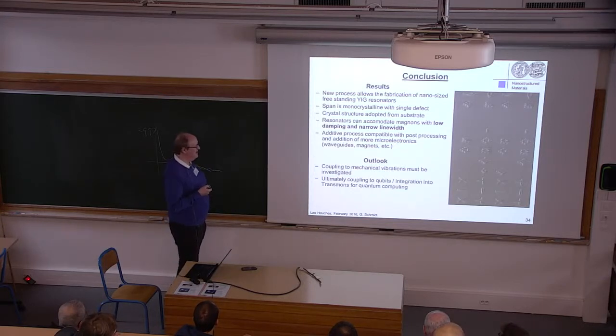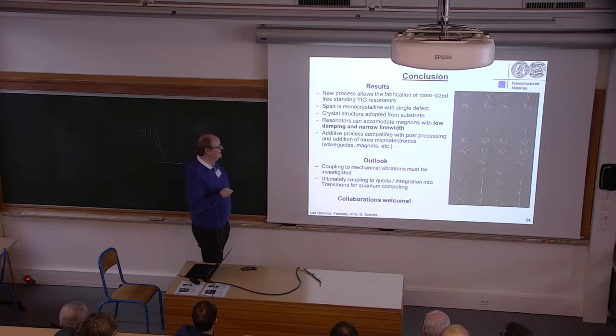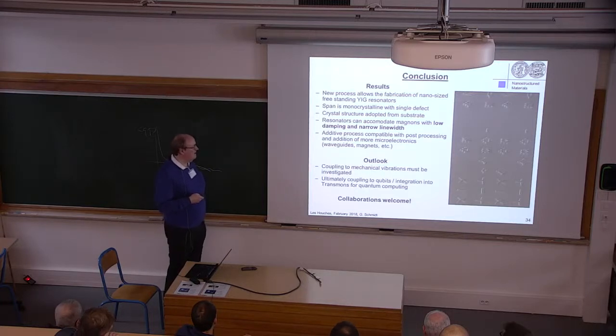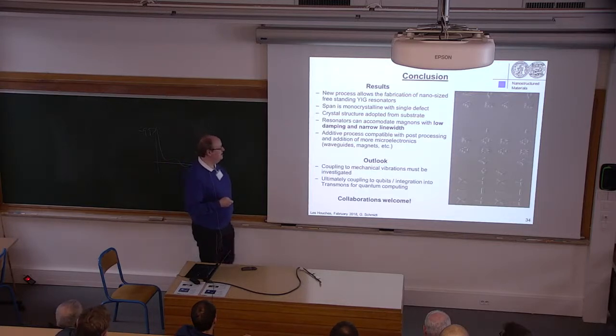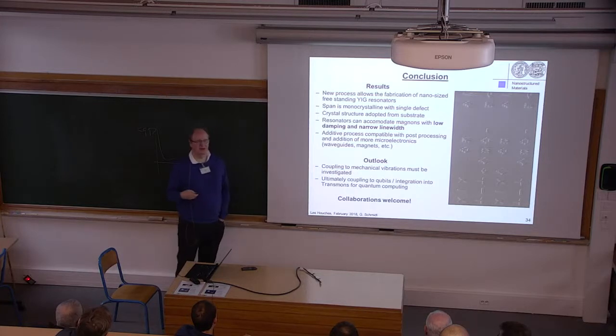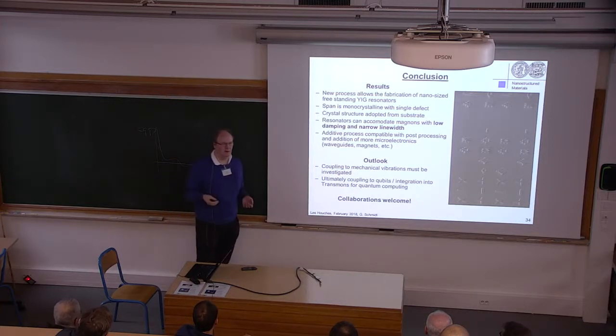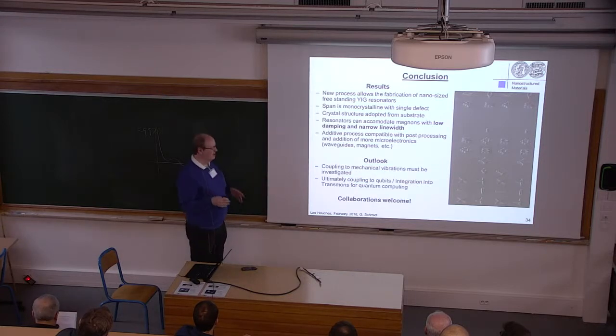But anyway, so the span is monocrystalline. That's the most important thing, because you saw the span of the resonance. And I don't know why this laser doesn't work. Now it's working. The crystal structure is adopted from the substrate. And you can accommodate in these resonators magnons with low damping and very narrow line width. And fortunately, the edges don't play a role in this one. And also the feet don't play a role in this one. It's just the span, which is high quality, where you want to have the resonance, and which will also have the mechanical resonance afterwards.